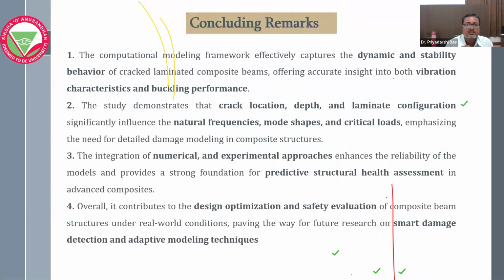So these are the concluding remarks: the computational modeling framework captures the dynamic and static stability behavior of cracked laminated composite beams, and offers accurate insights into both vibration characteristics and buckling performance, or static stability performance. Through this research, we can clearly explain the crack severity and crack behavior with respect to the laminate configuration, and the mode shapes and critical buckling loads, both can be realized.